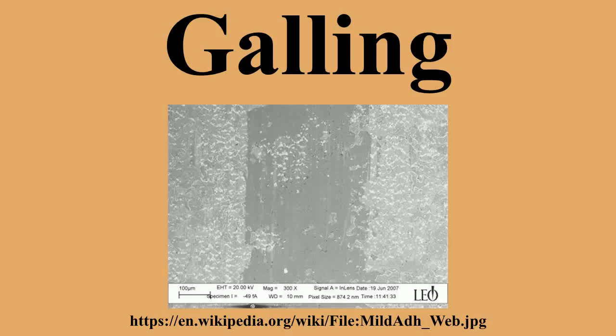As the lump grows, it pushes against the adjacent material and begins forcing them apart, concentrating a majority of the friction heat energy into a very small area. This in turn causes more adhesion and material buildup. The localized heat increases the plasticity of the gouged surface, deforming the metal, until the lump breaks through the surface and begins plowing up large amounts of material from the gouged surface.